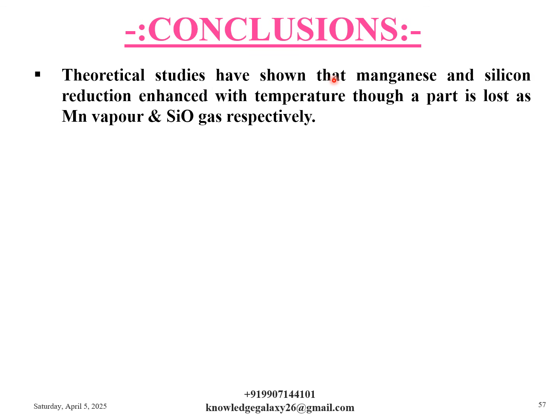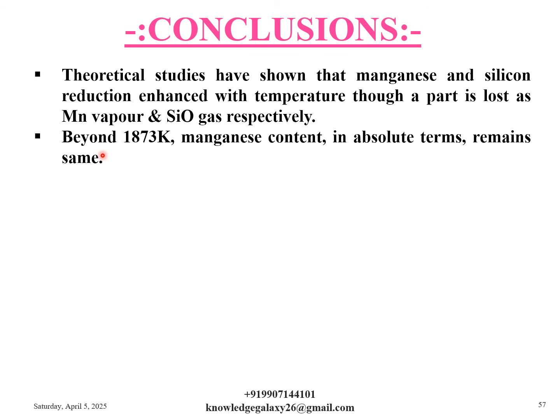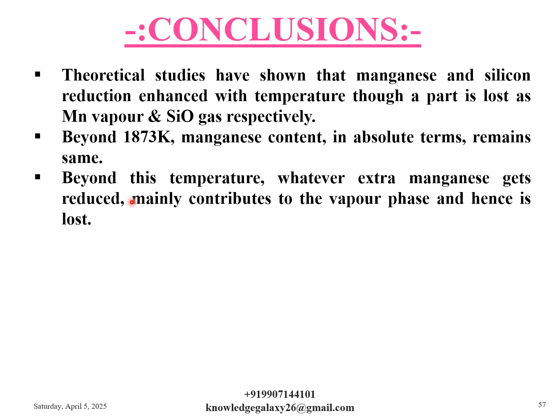Theoretical studies have shown that manganese and silicon reduction enhanced with temperature, though a part is lost as manganese vapor and SiO gas respectively. Beyond 1873 Kelvin, manganese content in absolute terms remains the same. Beyond this temperature, whatever extra manganese gets reduced mainly contributes to the vapor phase and hence is lost.